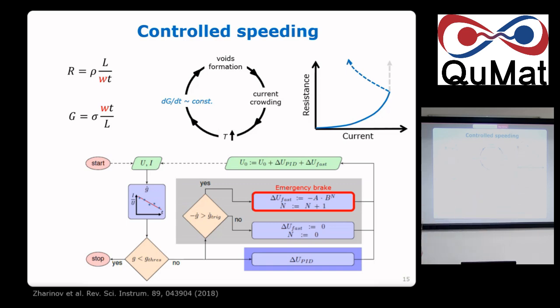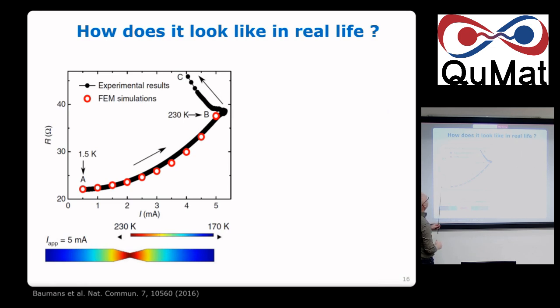So let me show you what it looks like in real life. So this is a case of aluminum. Okay? Look at the black curve, it is experimental data. Vertical axis is the resistance of the system. This is the current we are applying. We started with the system very cold. We cooled down to 1.5 Kelvin, and we start applying current. So what you see, resistance goes up. This is just because aluminum has a positive temperature coefficient. Okay, if you turn off the current here, you just come back on the same line. It's totally reversible.